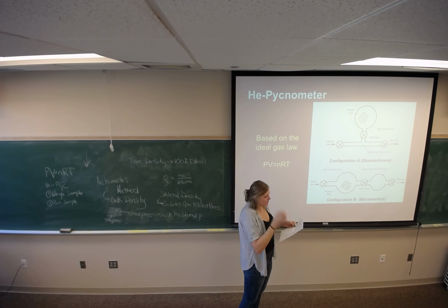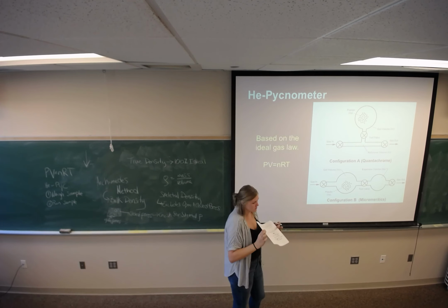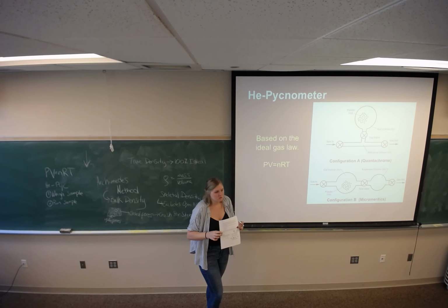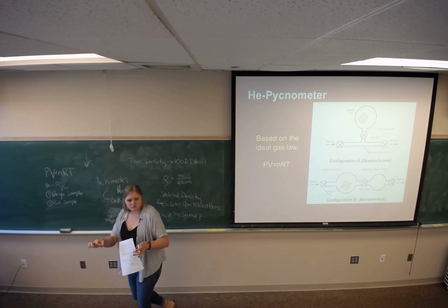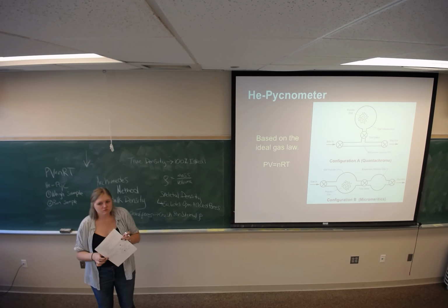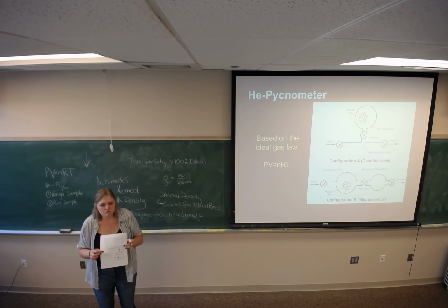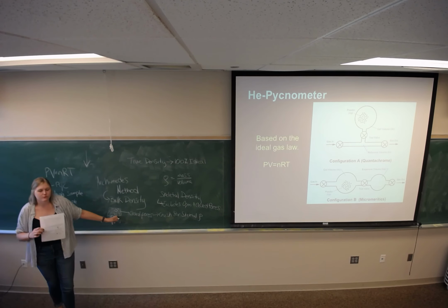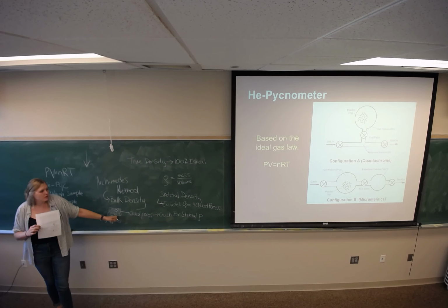Okay, so question 18 here: why would the pycnometer not be applicable for measuring density of a ceramic body after sintering? Can you guys answer that? Of a fully sintered ceramic body? Is it that gas hasn't permeated into the core? Yeah. So your closed pores, you're not going to have the gas fully infiltrate your closed porosity there. So it won't be as accurate.